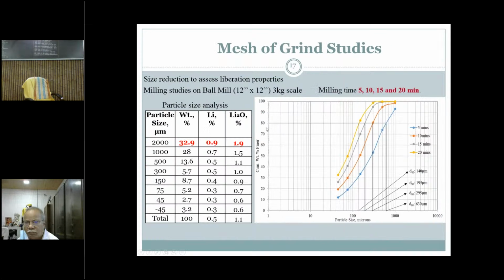Well, we subjected the material to crushing. Comminution studies have been carried out, and the material subjected to size analysis. You can see in the table, the first column shows the sizes, the second column shows the weight percentage retained on each size, the third column shows the Li content, and the fourth is the Li2O content of each size fraction. You can see the lithium content in the coarse size is a bit higher compared to the ultrafine size, especially 45 microns, which does not contain much Li2O content. The coarse fraction has more Li content.